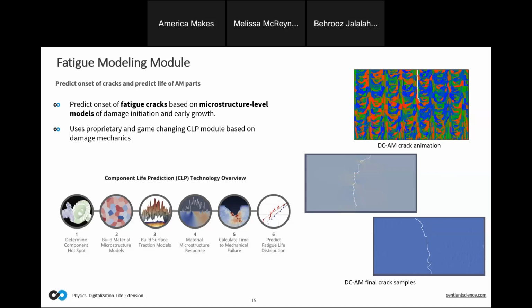Instead, in damage mechanics, you start from virtual pristine material, in the sense that you do not need to apply any crack there. There could be defects in the microstructure, of course, porosity, inclusions, voids, or even small cracks, but you do not need to apply that. And then you start from the damage that is accumulating at the grain level, on the grain boundaries. Those damages are growing, becoming more, creating dominant cracks. And then finally, those cracks convert to a long crack that causes the failure. What is the advantage here? The advantage is that with this kind of damage mechanics methodology, you could simulate the fatigue crack initiation stage, something that fracture mechanics methodology is missing.